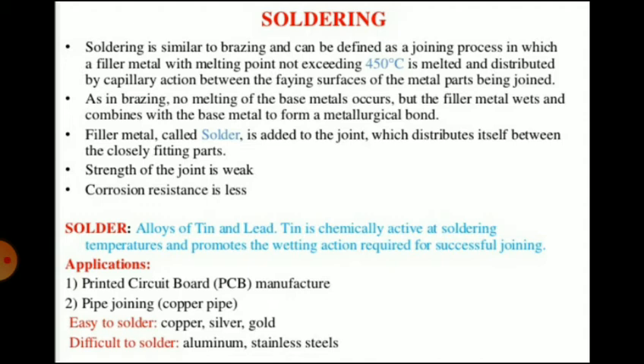The surfaces must be free from rust, grease, oil, and dirt by scraping with a dull knife or emery paper. Then align the components, coat the flux over the surfaces, and heat the soldering iron to 250°C to 300°C. The tip of the soldering iron is dipped into the flux and then tinned with the solder, which is applied to the parts being prepared for soldering. The most commonly used solders are alloys of tin and lead in various proportions.